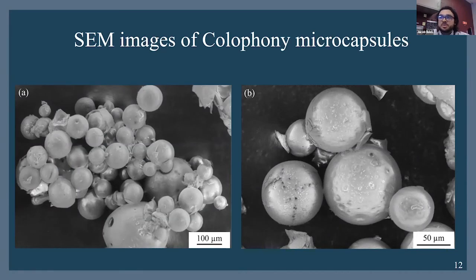After synthesizing microcapsules and imaging with SEM, we can see that they have diameters of around 87 to 90 microns, with a wide variation, which is well known for the solvent evaporation double emulsion technique, including some small pores on the outside edge. Now these pores will become more crucial when we get onto the release and some of the later slides on the effectiveness of the microcapsules. And here we see a close-up of a group of microcapsules, all spherical in nature with some dimples.